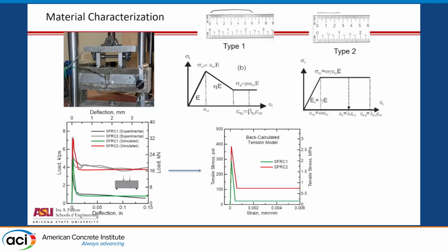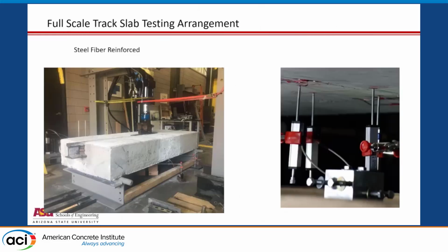But what we do is use a closed-form mathematical model for beams, which allows us to measure the tensile and compressive response of each sample. Once we plot the tensile response, we see that we can assume a residual tensile strength of about 0.75 megapascal, about 120 psi. That's all you need in tension. The other one with the lower fiber content was much lower, about 0.2, which is about 30 to 40 psi as our residual strength. This is what can be used in a serviceability-based type of model.